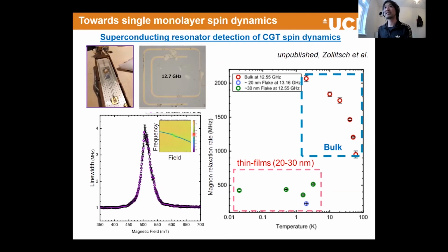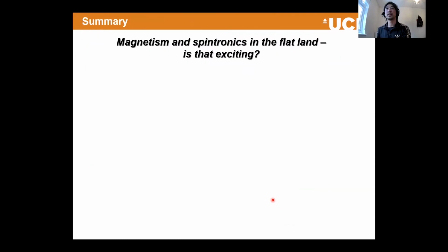Then we just try to listen to how this spin wave is excited. I'll skip everything through, but what I can highlight is that this magnetic relaxation rate is actually better in the thin film regime. So this is very pleasing to see. And we are excited about what happens in a truly monolayer regime. So then just wrapping up, this is a summary.